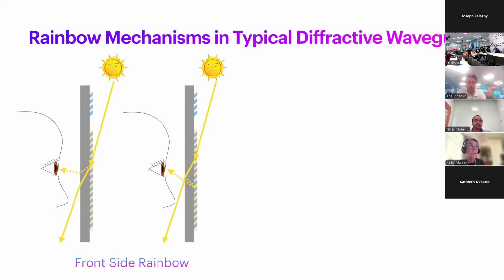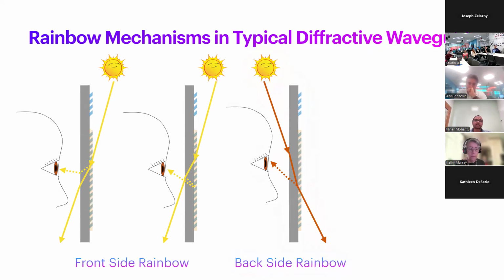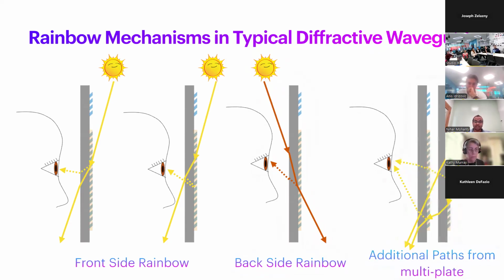The one where it diffracts once from the gratings, or the second where it could diffract twice after bouncing back and forth in the glass plate. In the case when the light source is on the back of the glasses, the single diffraction case is the one that produces visible rainbow intensity. All the other interactions have low enough intensity to be invisible. However, when there are multiple plates, there is a combination of many paths that reaches your eye, both from the front side and the back side. And increase this to more plates, let's say 3 plates, the rainbow goes up significantly.